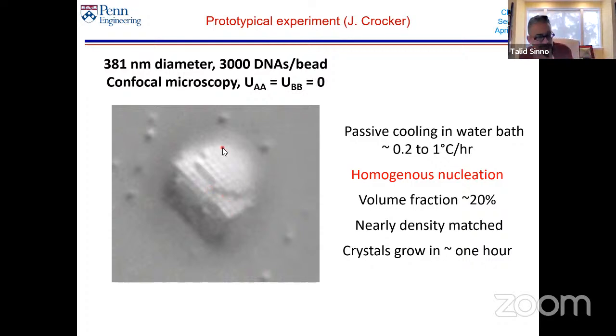The way this is done is the particles are put into solution, and then the temperature is gradually lowered in time until the interactions become strong enough relative to the thermal energy. At some point, the particles start homogeneously nucleating into little crystallites. The crystallites then continue to grow. While each particle is pretty density matched so that it floats in solution, eventually these crystals become large enough that this very slight density mismatch means the crystallites fall out of solution to the bottom of the vial, at which point they stop growing.